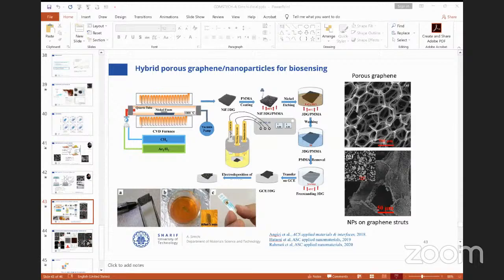We use CVD, chemical vapor deposition, and we created three-dimensional, highly porous graphene on the surface of nickel foam, and then remove the nickel foam and prepare freestanding three-dimensional graphene, and then functionalize the surface.